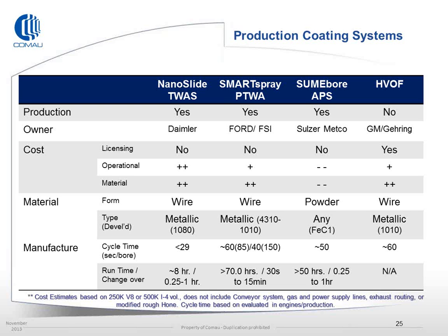In terms of running time and changeover time, the LDS is limited by the wire that's carried on board. Smart spray we feed from an external wire supply, and we're able to butt weld the wires, so we never have to shut down for a wire feed or change. For us, the time that we have is really the interval to change the arc torch, which has a life depending on how you're operating. If you're operating with a constant start-stop operation, it's 70 hours, and it pursues up to 100 plus hours if we run continuous on the torch life.